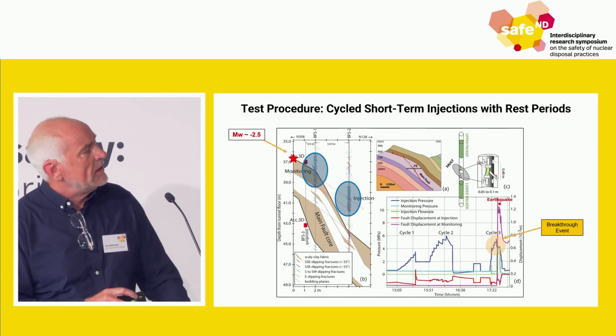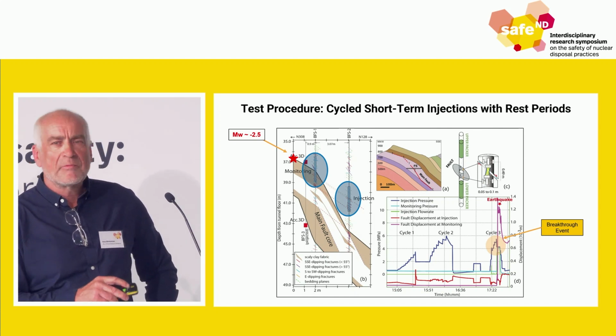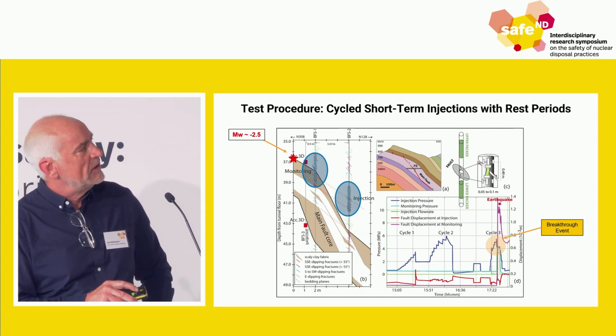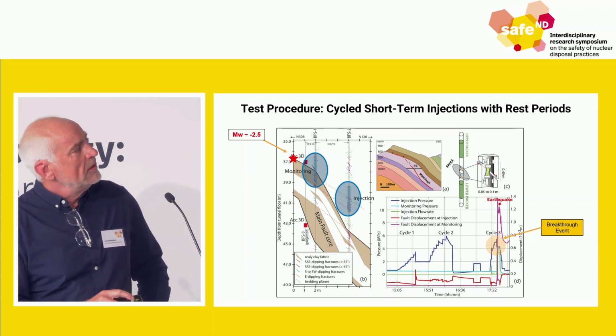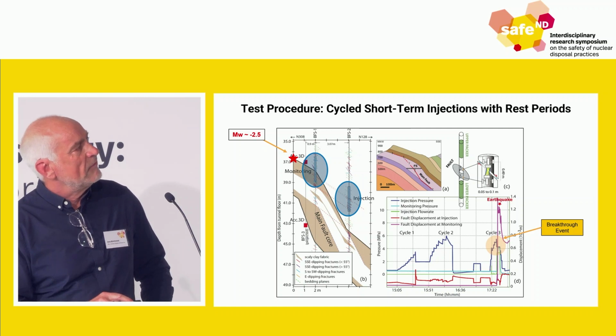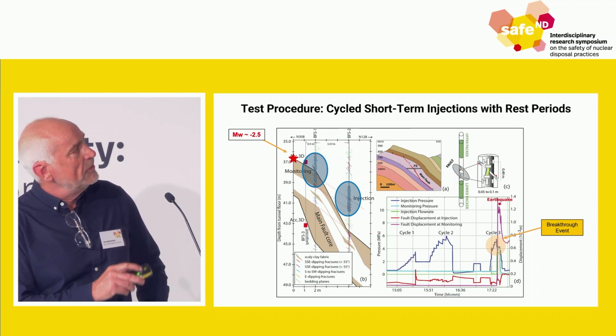We typically did short-term 30-minute cycling. We increased stepwise the pressure in that chamber, then stopped, increased a little higher, stopped a little. And then in the third round here, we were in fact getting a breakthrough.